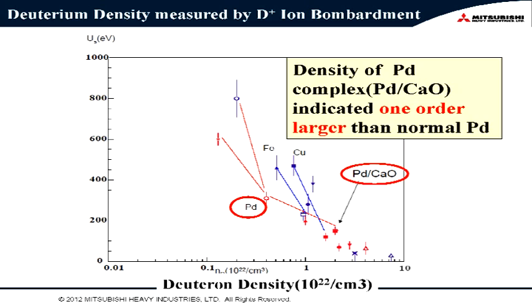This axis means the deuterium density estimated by the normal DD reactions. This is normal palladium, and this point corresponds to palladium with calcium oxide. So it suggests that the deuterium density of the palladium complex is one order larger than normal palladium. So our multilayer thin film seems to have much more deuterium in the surface.